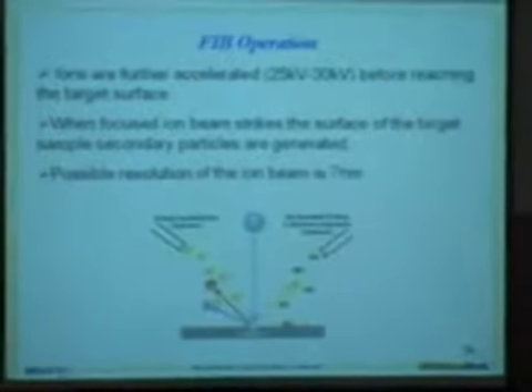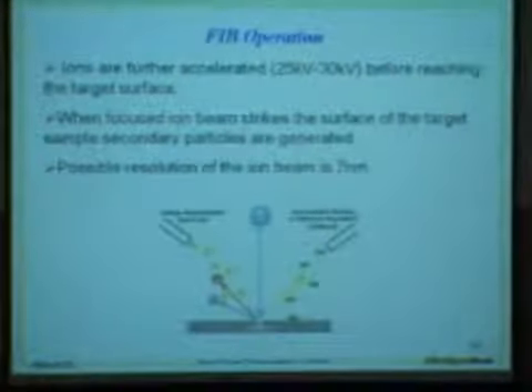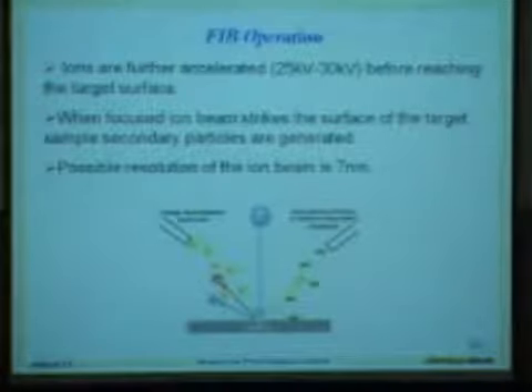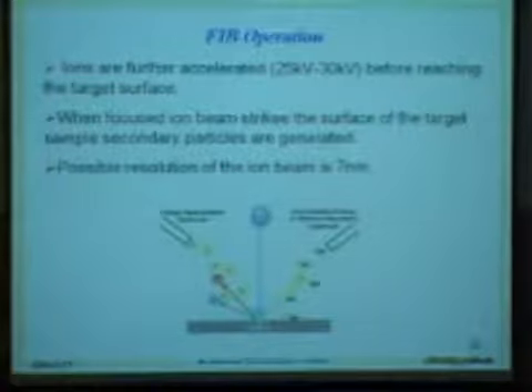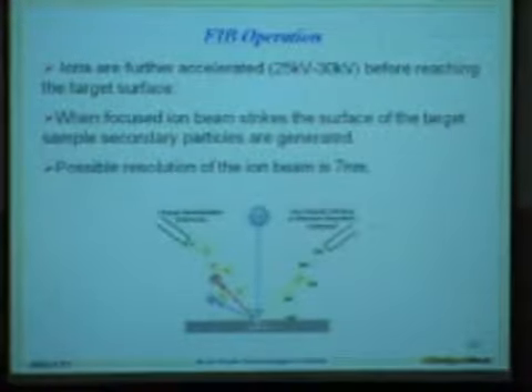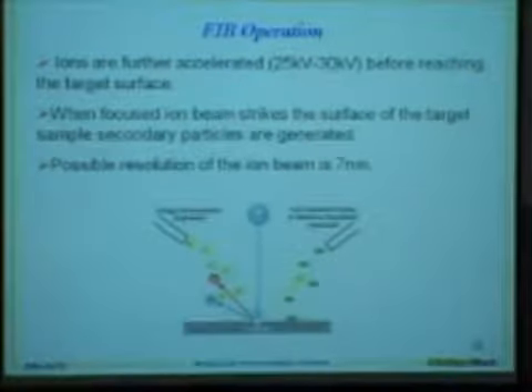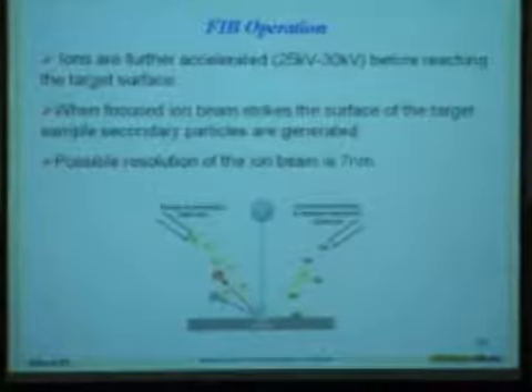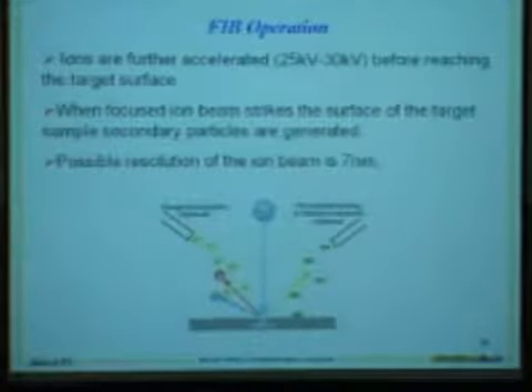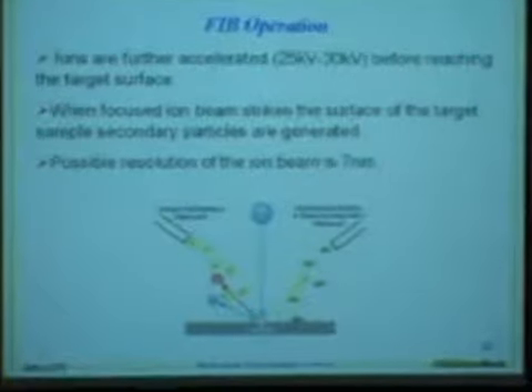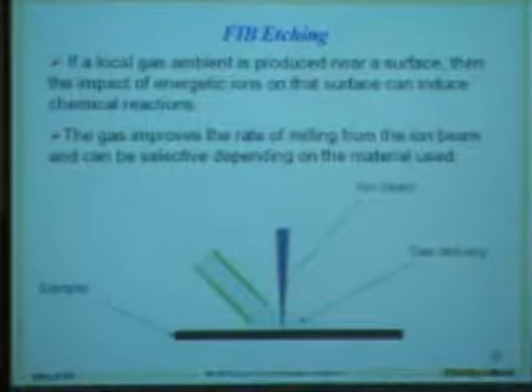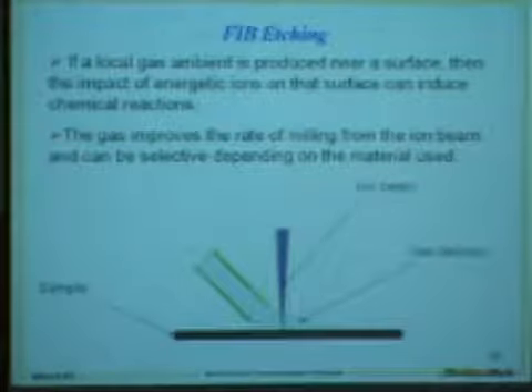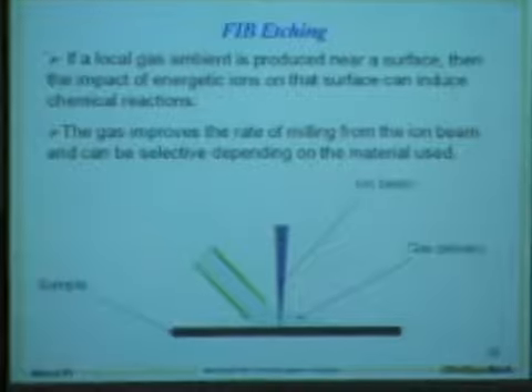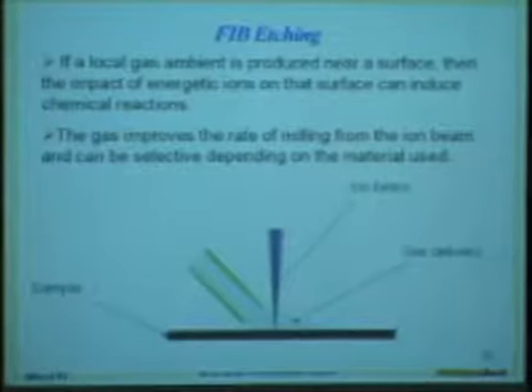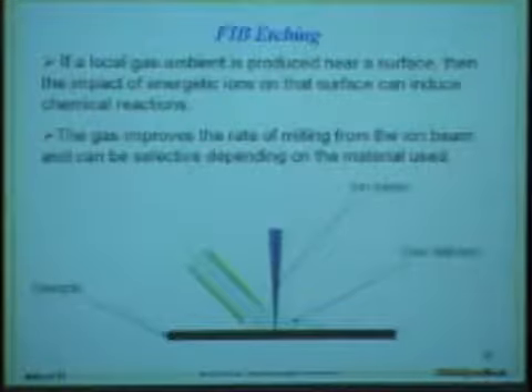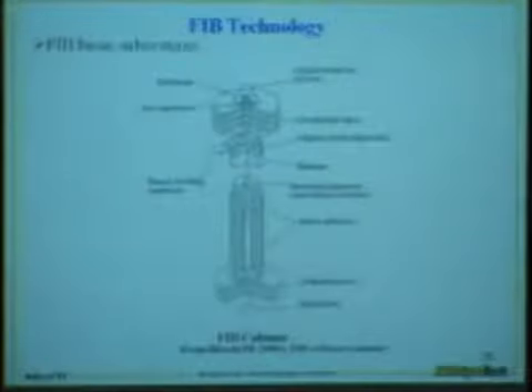So when focused on the surface, they have the possibility of producing one of 4 different things. They can sputter etch the surface, they can produce heat in the substrate, they can implant themselves into the substrate, or they can be used to decompose a gas at or near the substrate. So in an etching condition, the ions, as they reach the surface, primarily serve to heat and sputter the material from the surface, and this is called the ion milling technique that you may be familiar with.